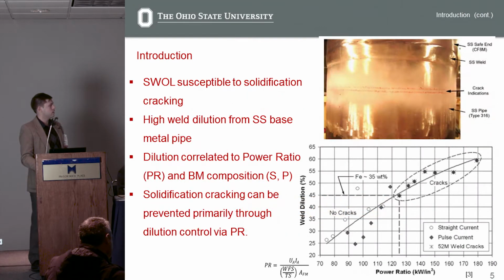Well, the repair solution itself is not without its own problems. There have been numerous studies that have presented the solidification susceptibility of the filler metal 52M. And what this presents as is crack indications that are breaching the surface of the structural weld overlay. And these cracks have been associated with high dilution of the filler metal 52 or similar alloy with the cast stainless from the base metal.